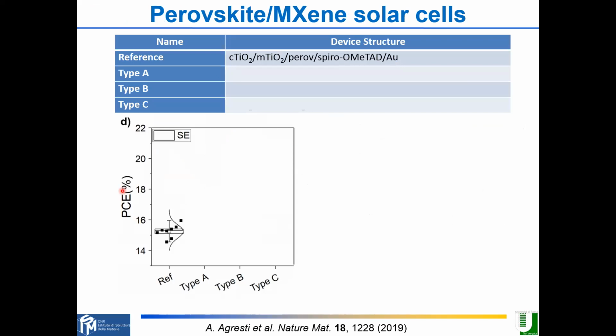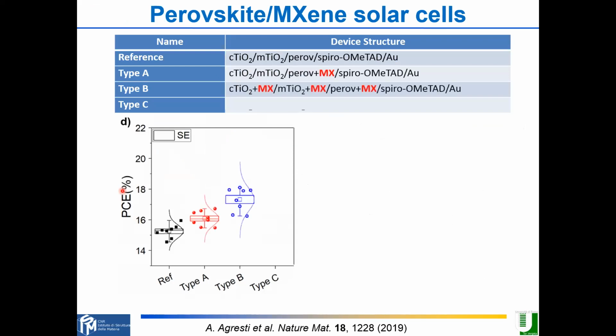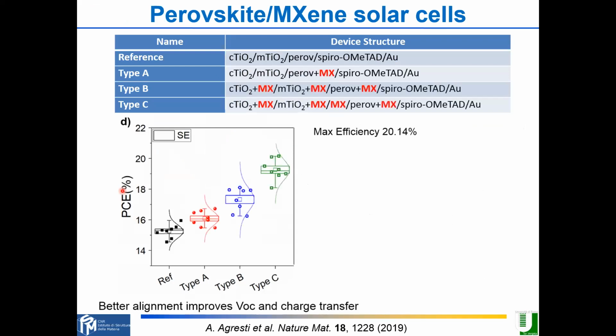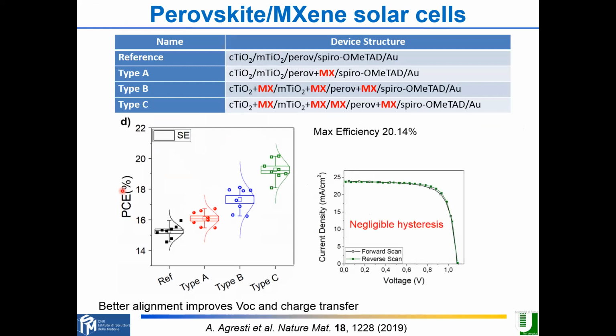This was the efficiency of a conventional solar cell, and then we applied the MXenes at different points, also guided by simulation. We were able to push the efficiency for a simple perovskite up to more than 20%, and we completely reduced the hysteresis of the cell. So this is a practical technology. We are applying this now in many other devices. There are other publications I would prefer not to show here, also on the stability of the cell.